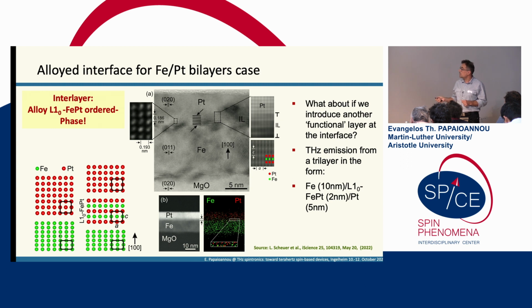Here you see the transmission electron microscopy images. For the magnetic people, this is very well known. It's an old friend. People tried in the past and nowadays to fabricate this alloy because it is one magnetic material with the highest magnetic anisotropy. Here you see also the structure. In principle, the iron and platinum atoms form this layered structure of the L10 ordered phase of iron platinum.